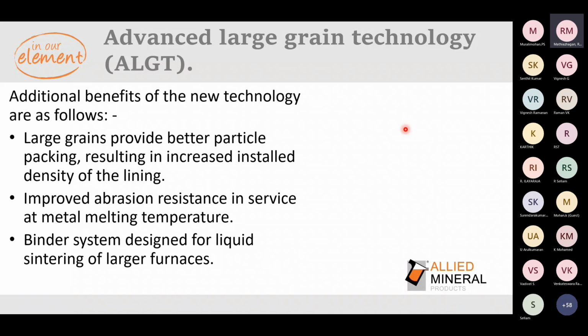So when it comes to the additional benefits, better packing density is attained because we had some cases where we removed the foam even without introducing any kind of heat. We don't normally recommend it, but there was one customer who did it. The idea of sharing this is that this product compacts so well that you can actually remove the foam also. But normally it's not recommended because it's unsafe.